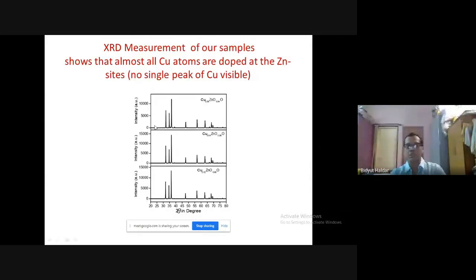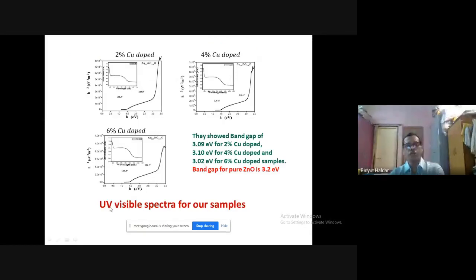Now coming back to our samples, we have taken the XRD, and these X-ray plots are shown here. UV-visible spectra of our samples were also taken, which show that the band gap for pure ZnO, we know, is around 3.2 to 3.4 electron volts. However, for the 2% copper-doped sample it becomes 3.09 electron volts, for 4% it is 3.1 electron volts, and it is 3.02 electron volts for the 6% copper-doped sample.